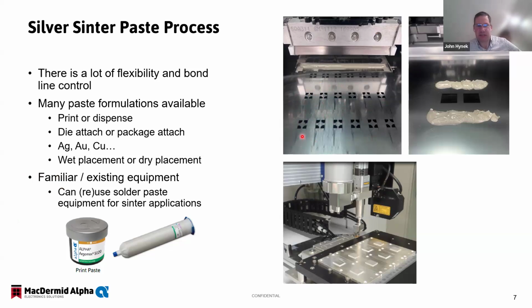So you can see here, it doesn't necessarily have to be a square. In this particular example, there are some rounded corners here, which is a big advantage that you get with paste, that you can place the paste exactly in the same geometry as the component requires. And then this one, you can see an application more geared for large area package attach. The other big advantage you get with paste is you can also do a dispensing process if that's what you want to do. And that's what we're trying to show here with this picture.